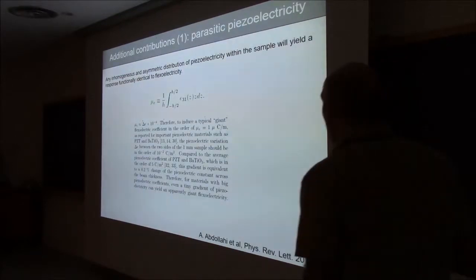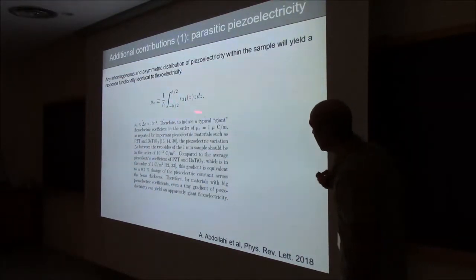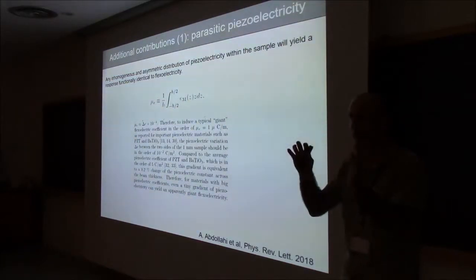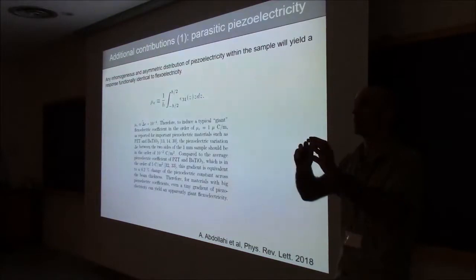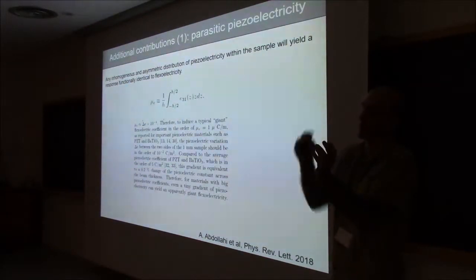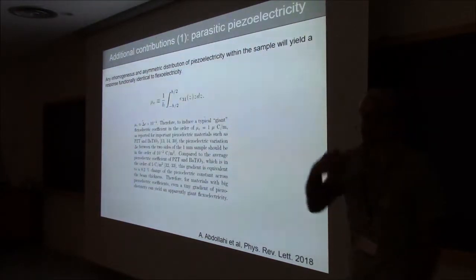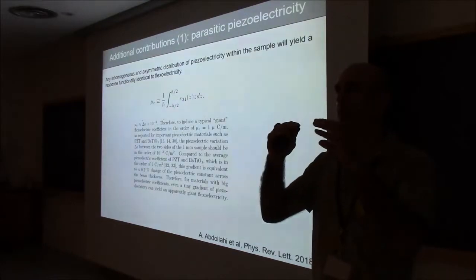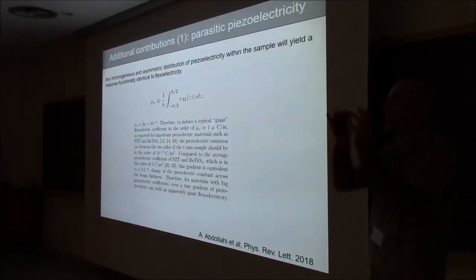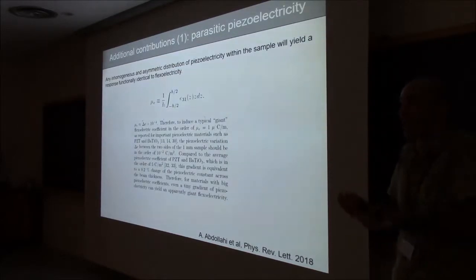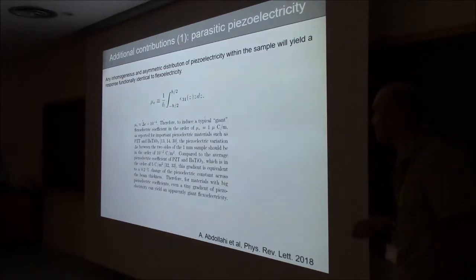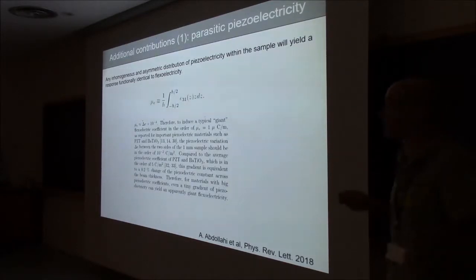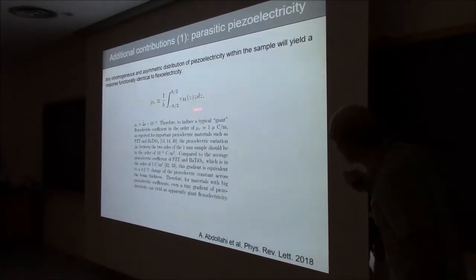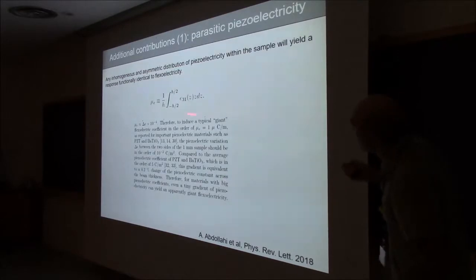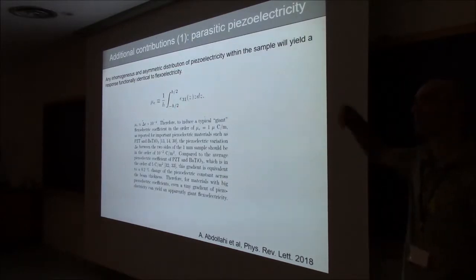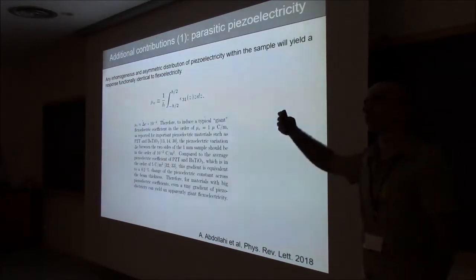Okay. I've mentioned earlier that if you have a material that is piezoelectric and perfectly homogeneous and you bend it, there is no net deformation because the extension on one side cancels the compression on the other, so you should not expect any piezoelectricity. But if your material is not perfectly homogeneous, say it's a little bit more piezoelectric at the top surface than at the bottom, and that is quite often the case because you have gradients of defects, for example, then when you bend it, you will measure an effective flexoelectric coefficient that is basically the integral of the distribution of piezoelectricity. Okay, basically it's proportional to the asymmetry in the distribution of piezoelectricity.